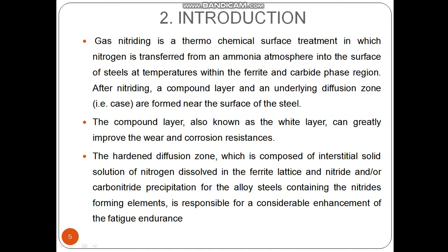Introduction. Gas nitriding is a thermochemical surface treatment in which nitrogen is transferred from an ammonia atmosphere into the surface of steels at temperatures within the ferrite and carbide phase region. After nitriding, a compound layer and an underlying diffusion zone are found near the surface of the steel. The compound layer, also known as the white layer, can greatly improve the wear and corrosion resistance. The hardened diffusion zone, which is composed of